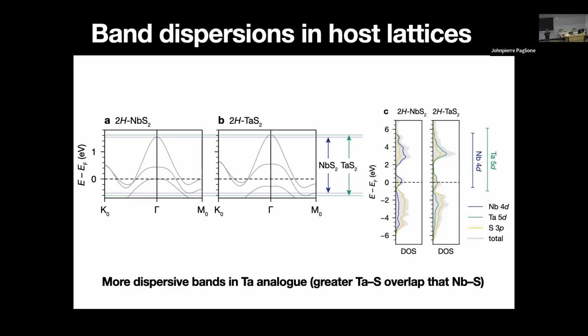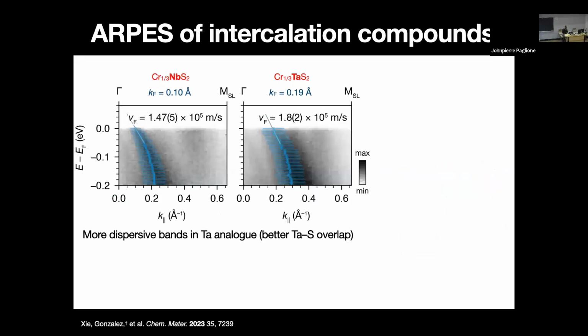And this is because the tantalum d orbitals are larger. Its valence d orbitals are larger than those of niobium, and also energetically there's a better match with sulfur, and so you end up with better overlap between the orbitals of the tantalum and those of the sulfur. That overlap is what is dictating the spread of the bands in your electronic band structure, as Leslie was showing with the Hoffmann type tight binding model.